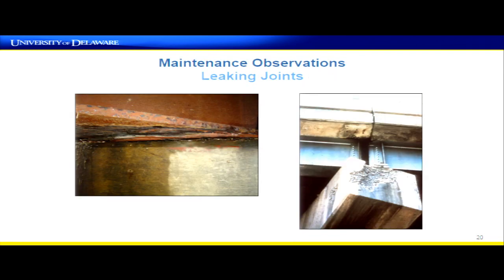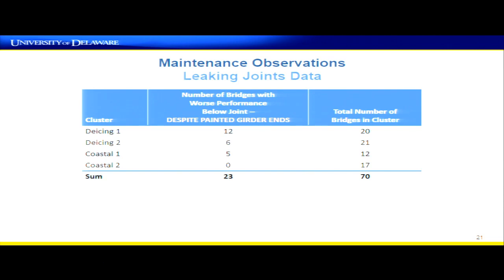All right, very quickly, a couple of comments and observations based on maintenance and detailing. By far, both on field inspections and the long-term bridge performance program data that we looked at, the biggest contributor to corrosion of weathering steel has nothing to do with humidity or de-icing agents directly. It has to do with a leaking joint. This is the bottom flange peeling off at an abutment underneath a leaking joint. This is also obviously not a problem that's limited to weathering steel. All of our materials are going to suffer when they're under a constant wet environment.